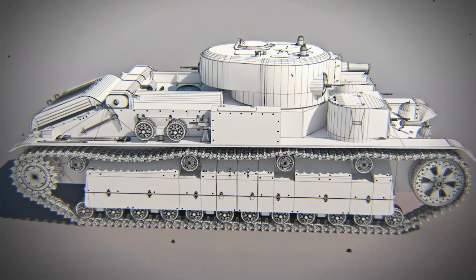Moreover, problems emerged at the tank assembly plant. Homogeneous armor turned out to be very sensitive to welding. The plates warped due to the thermal effects of welding. At the edges of the parts, cracks appeared, and the welded seams chipped off. Nevertheless, it was from this material that the hulls of the T-28 tank were made.